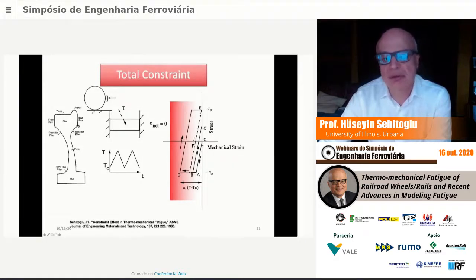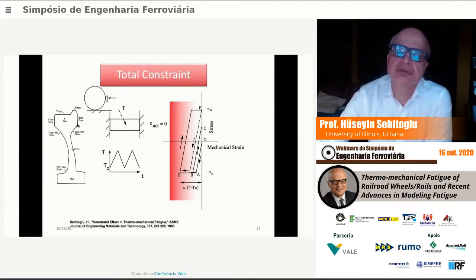So when you heat, you go into compression here from zero to A. And if your temperatures are high enough, it will yield. Then you flow plastically from A to D, and then you cool down and unload elastically, and you could yield in tension and get a tensile residual stress. So that's what's happening in the railroad example. It's a very, very simple approximation in terms of showing this model. But we have tensile residual stresses.